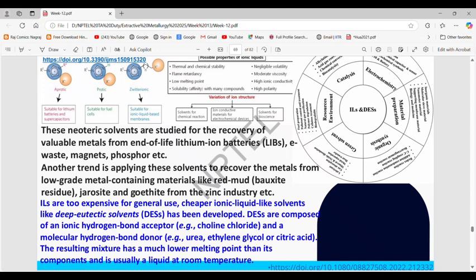These are basically in the solid forms. But when we mix them in a predefined proportion, due to the eutectic points of these particular mixtures, this mixture is going to attain a liquid form at room temperature, and in the liquid form we can easily go for the leaching processes with the help of these deep eutectic solvents. So we are working on the eutectic points. That's why these solid mixtures are known as deep eutectic solvents. So one part of the mixture will be hydrogen bond acceptor, which is majorly choline chloride, and one will be the hydrogen bond donor, which can be urea, ethylene glycol, or citric acid, or oxalic acid, or formic acid, etc.